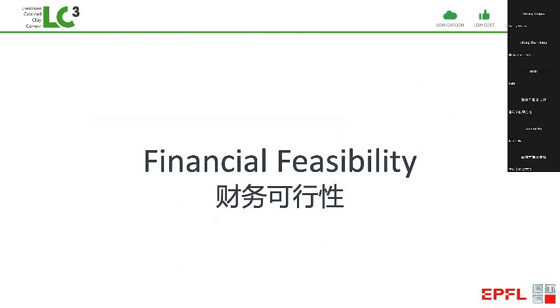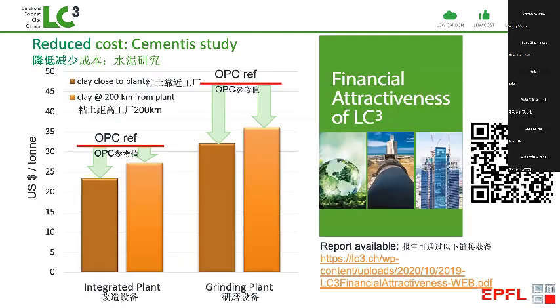On the financial side, we also have very good news because the calcined LC3 is generally cheaper to produce than the reference Portland cement. Even if you have to transport clay 200 kilometers from the plant, you can still save on your operating costs regarding OPC reference. A particularly good scenario is if you have a grinding plant in areas where you don't have limestone, so don't have good clinker production. You can really decrease your need to import clinker and get a very good material by using local clay. Now, this calculation we made a few years ago in 2019.